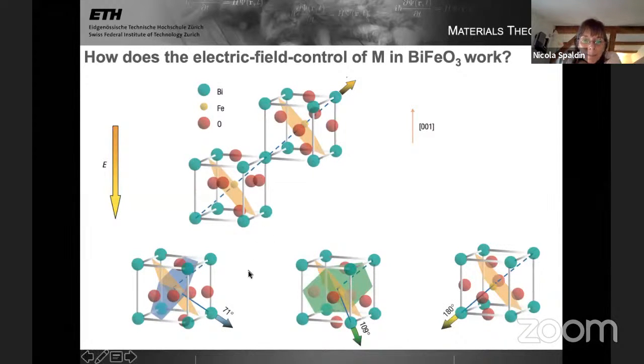And so look at what happens to the easy plane of the magnetization. It starts perpendicular to 111, then it rotates so it's perpendicular to the new polarization axis, and then the magnetism has to come with it, right? The new easy plane of magnetization has come around to here, then it rotates to perpendicular to the second intermediate axis and ends up rotating all the way around. So the switching of the magnetism is, I'd say, a kinetic process. It's not really a thermodynamic process. The magnetism doesn't care. It wants to be in this plane. It doesn't care whether the polarization is here or here. But during the switching process, it gets dragged around. So you could argue it's not really a magneto-electric effect. It's an electro-elasto-magneto effect in this case.